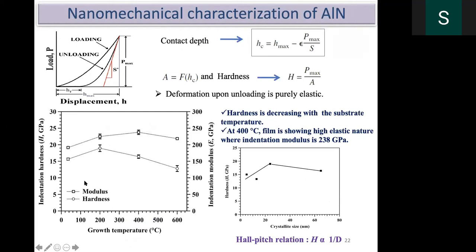So possibly one reason is the grain size. You can see the grain size versus hardness plotted here. Hall-Petch is a very famous relationship. When you decrease the grain size, the strength or hardness of the material changes. That means if you decrease it, the hardness increases. Unfortunately, that cannot go on endlessly.